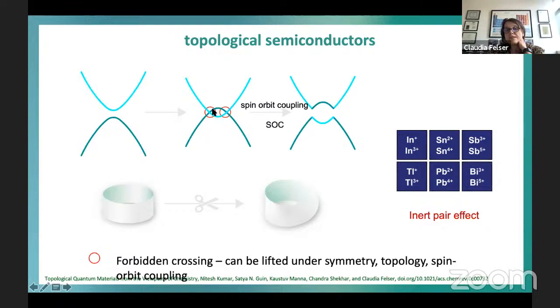Here, since we have topological materials, we have large spin-orbit coupling because we like to have heavy elements. So then this crossing is forbidden, and we can open up a band gap by spin-orbit coupling.